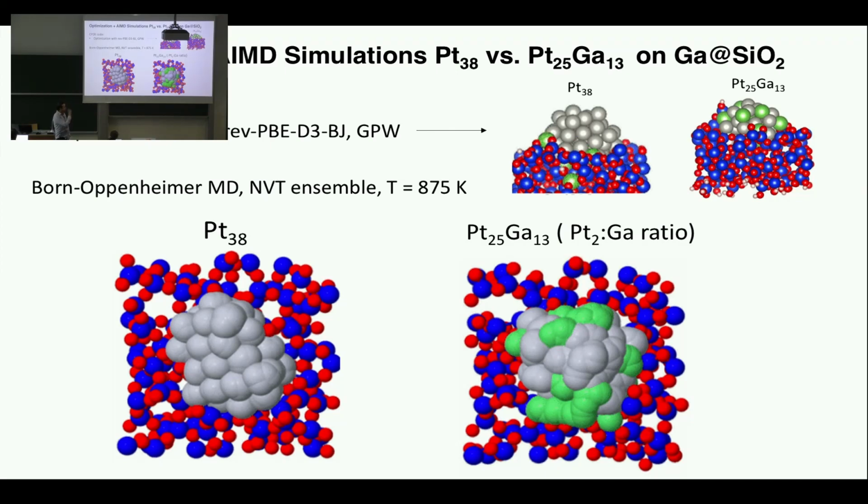Okay, I see. I didn't explain a lot, but it's the way you synthesize the catalyst experimentally. They graft gallium on silica, then they deposit platinum. They cook it up, and they form these platinum to gallium particles, but you still have some gallium in your support that stays there. It's also true that we checked a bit of where platinum wants to sit at the beginning, and the platinum you put interacts more with the gallium you have already in there. That's why you have some green atoms also nearby the platinum.